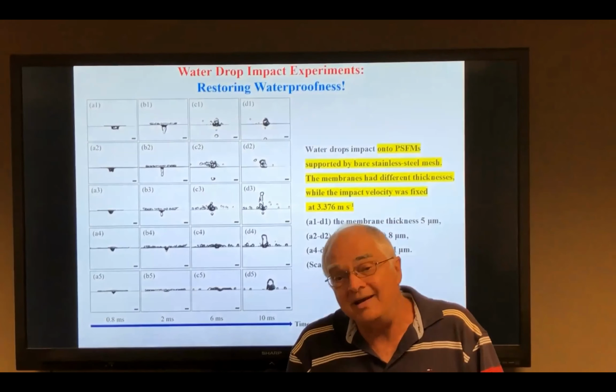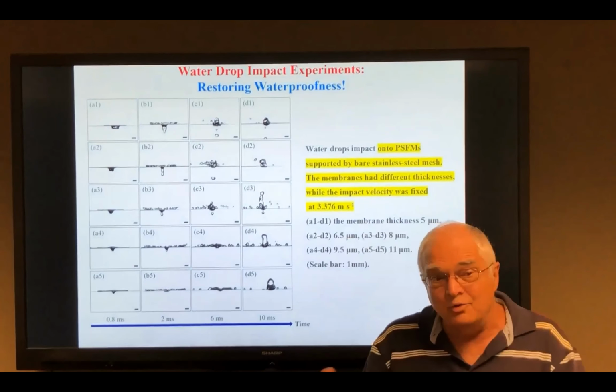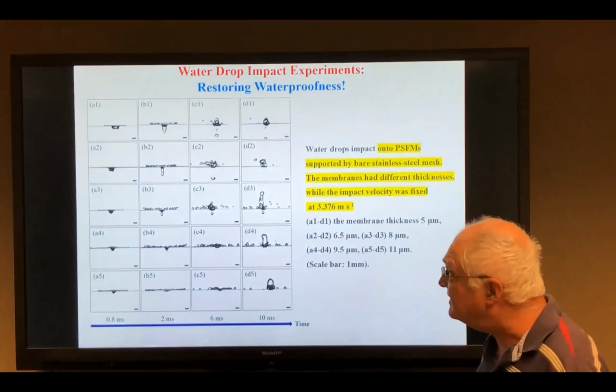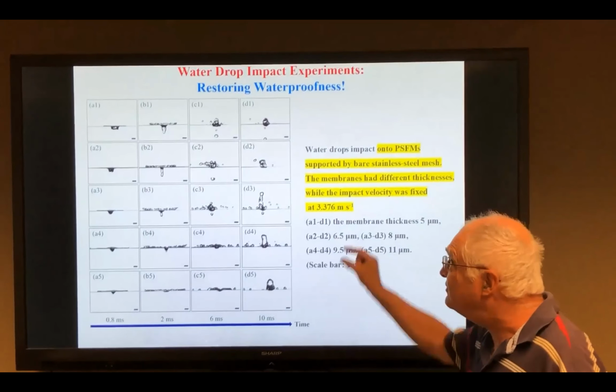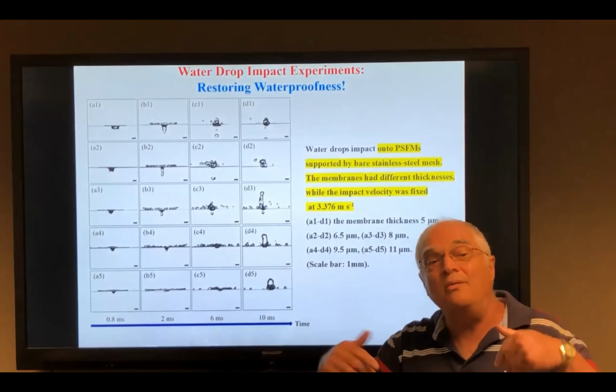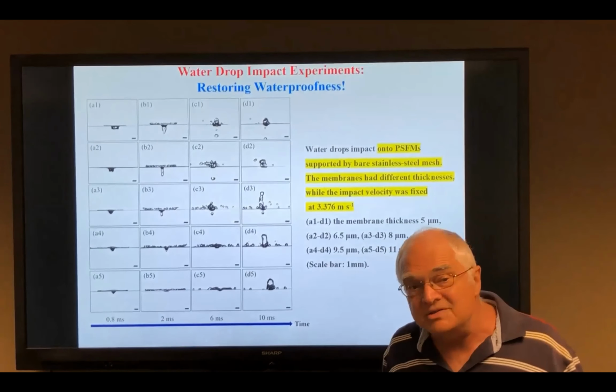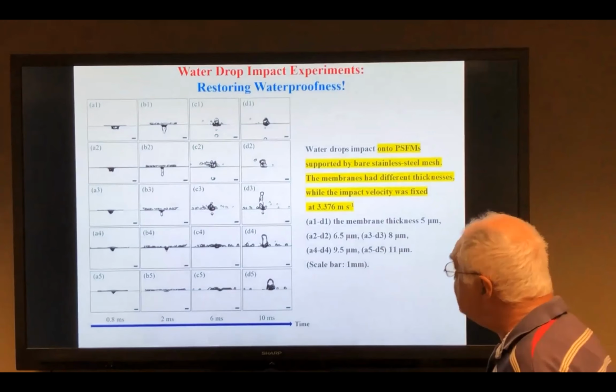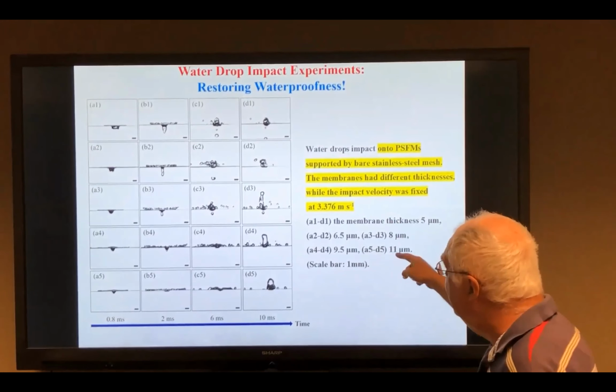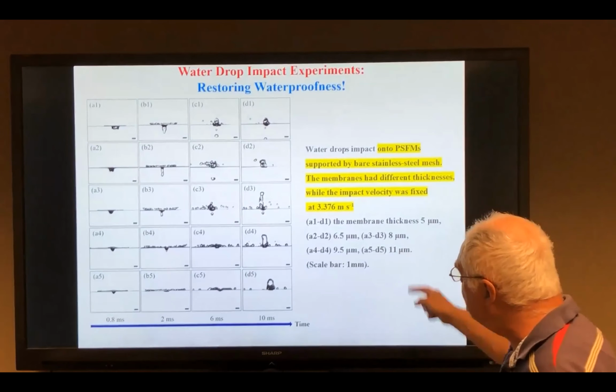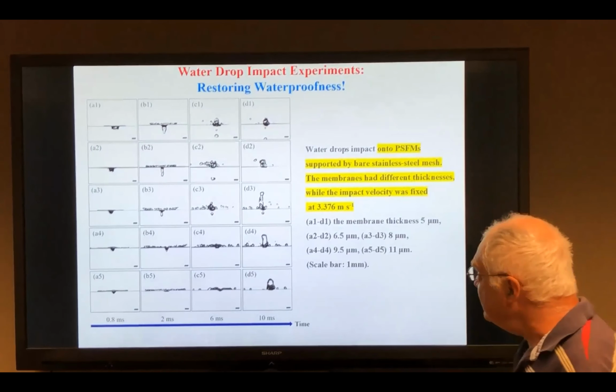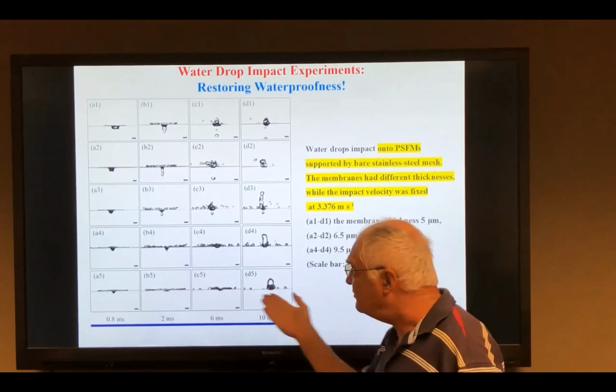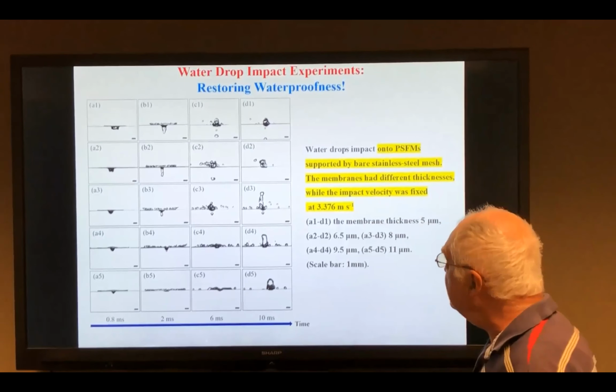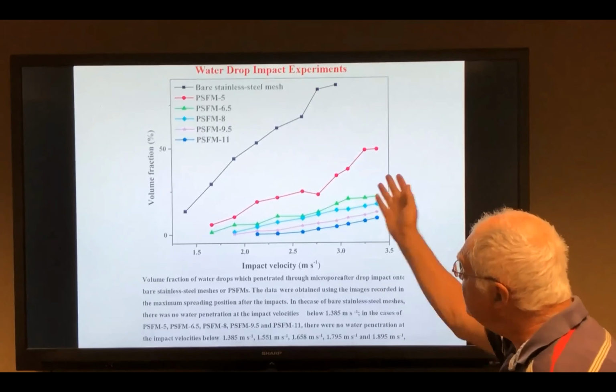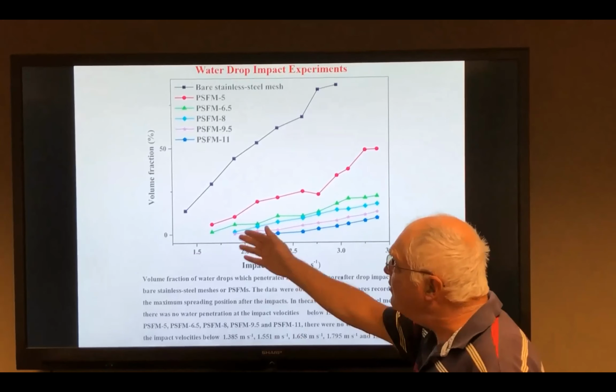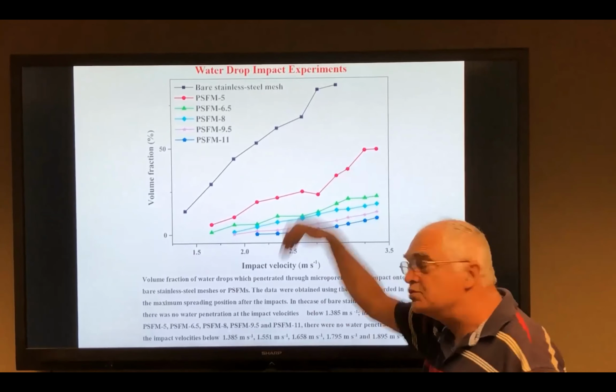The idea is to make the membrane as thin as possible to protect against water droplets, but you see that it's impossible to do. Then you have to go thicker and thicker, to stop water from penetrating through viscous dissipation. When you go to higher thickness, for example, here there is a demonstration up to 11 micron thick membrane, you can prevent water from practically going through.